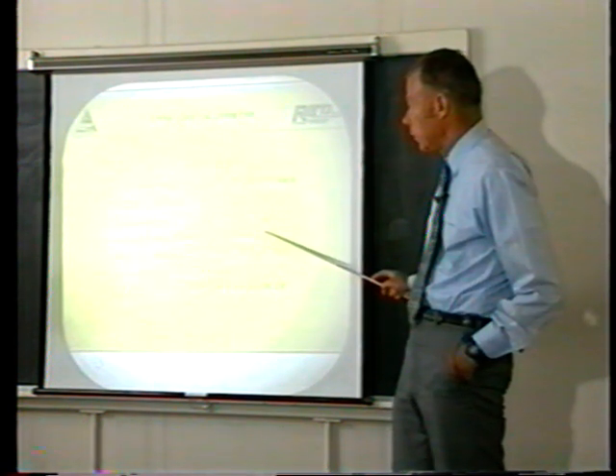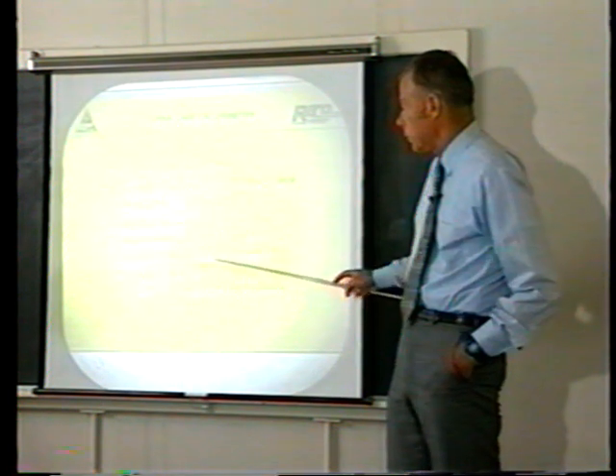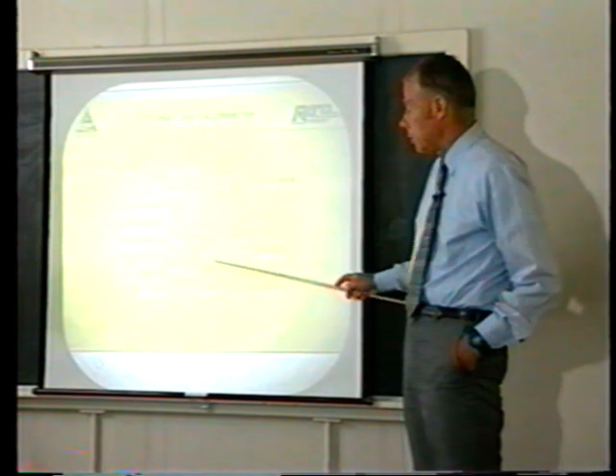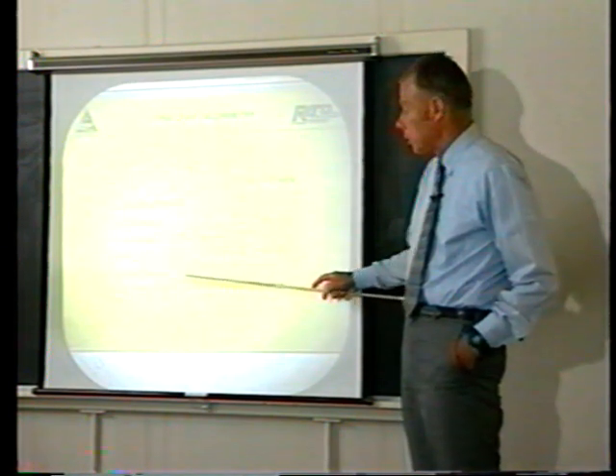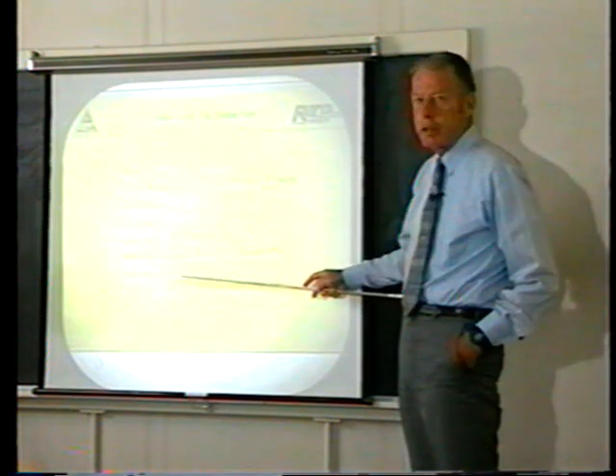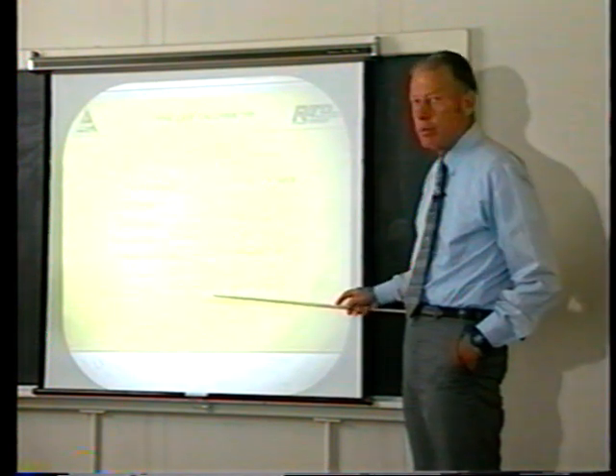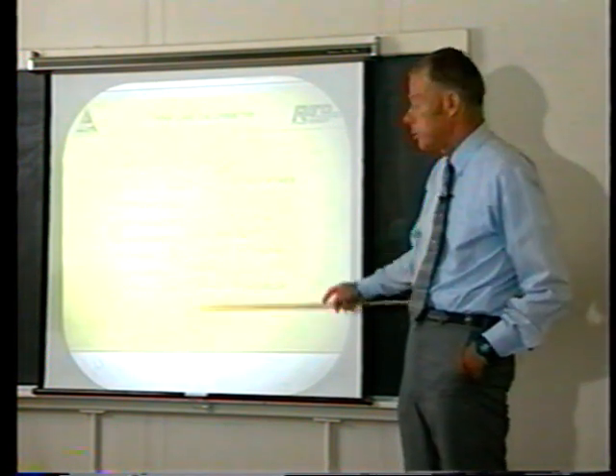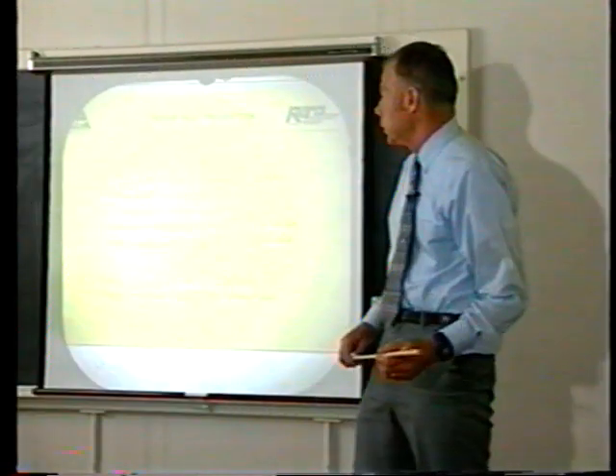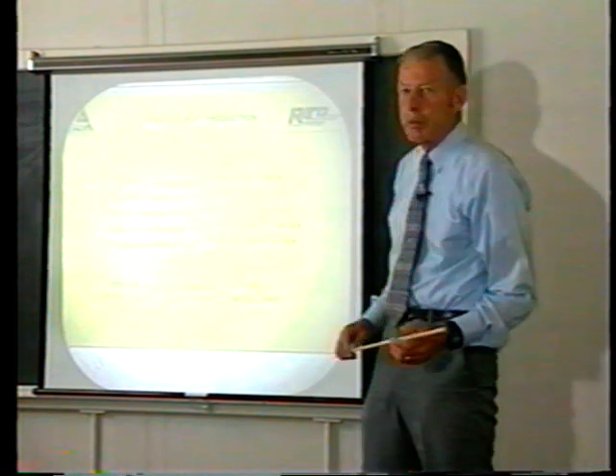The Faraday efficiency is always important to measure accurately. This was always checked by the rate of gas evolution, measured volumetrically as it came out of the cell by displacement of water. We also measured at the end of each day the volume of D2O added and compared it to Faraday's law. And we could always see the rate of gas flowing through the oil bubbler that we used. So we always had 3 checks on the Faraday efficiency in every experiment.